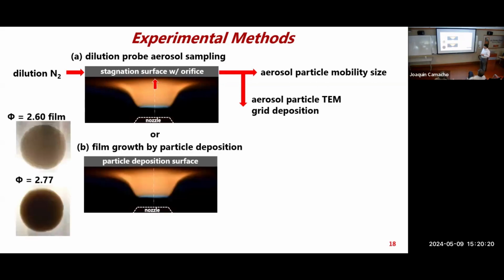Another measurement uses a different sample collection technique. It's just a direct deposition of the particles on this plate. So we can just mount one of these plates on there, and over time it'll grow a film just as a stagnation surface. It's like chemical vapor deposition, but instead of the gas phase precursors growing into a film, it's just particles sticking onto the surface to form a porous film. And we'll analyze this.